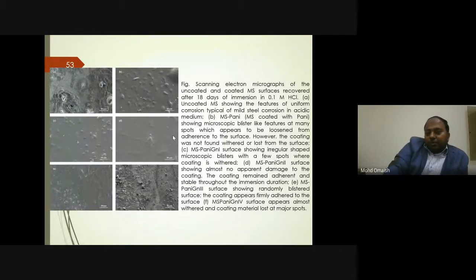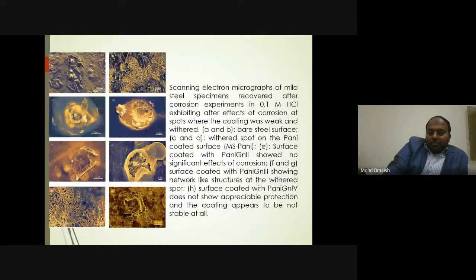You can also make polyaniline paints, and you can easily coat surfaces with a brush. And these are also some images showing pit corrosion, and in the case of polyaniline graphene, the corrosion has reduced.